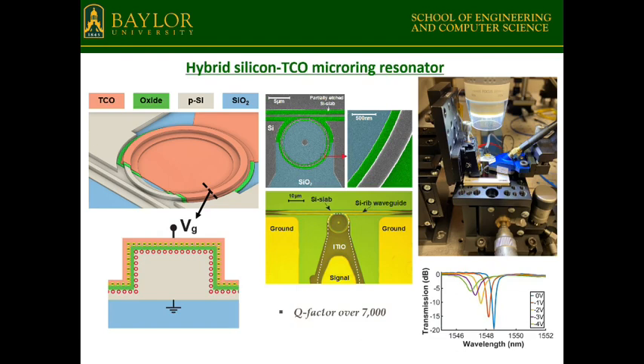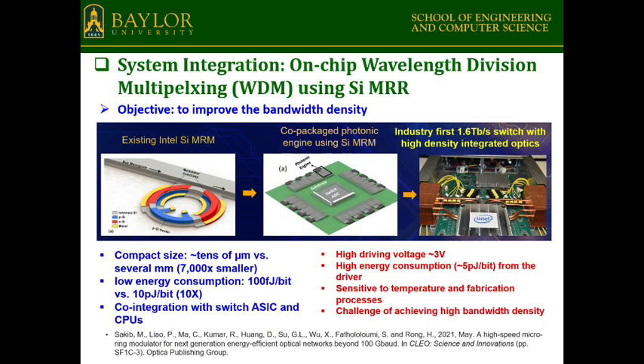And this is the device fabrication, and this is one of the devices we fabricated, and this is the optical imaging showing the fabricated device. You can see this is the ring here, and this is the waveguide, and this is the electrode where you can apply the electronic signal, and this is the testing setup, and this is the transmission curve when you apply different voltages. And you may ask why you want to use a micro ring compared with the nano cavity. The reason is called the bandwidth density. People have already shown you can use a micro ring to form a commercial modulator, and this is actually from Intel. Intel has already developed this micro ring resonator modulator, and it's already being used in a commercial product.